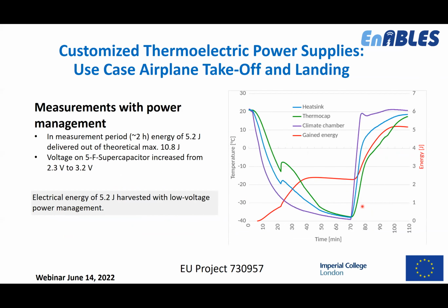So actually here is then the same measurement as before, but here we're showing the output energy during that full cycle of 2 hours. So during that full measurement cycle of 2 hours, we were able to harvest 5.2 joules. This is nearly 50% of the theoretical maximum of 10.8 joules, and with that energy we were able to charge a 5 farad supercapacitor from 2.3 volts to 3.2 volts.